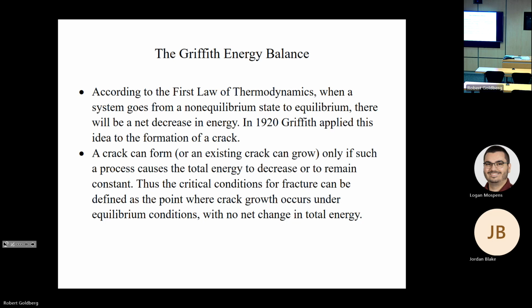But anyway, in the Griffith method, he follows the idea that according to the first law of thermodynamics, when a system goes from a non-equilibrium state to an equilibrium state, there'll be a net decrease in energy. And in 1920, Griffith applied this idea to the formation of a crack. So basically what this means is a crack can form or an existing crack can grow only if this process causes the total energy to decrease or to remain constant. Can't create energy. So the critical conditions for fracture are defined as the point where the crack growth occurs under equilibrium conditions with no net change in total energy.